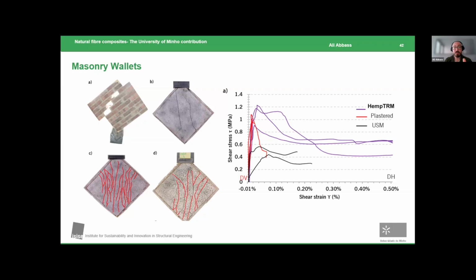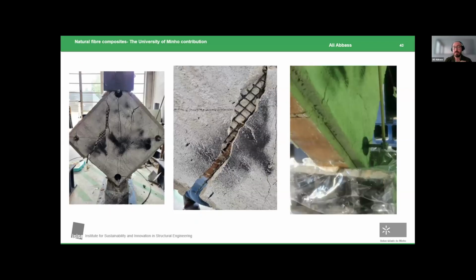The plastered ones, although they achieved nice shear stresses, had zero ductility technically. In the non-reinforced wallets, you would see this kind of super pseudo-ductility, and it's not related to the structure itself. It's just for the strut effect, so it's not real. So the purpose of the fiber inclusion in the composite system was super achieved. Here you would see some fiber ruptured upon the testing, although we have observed some kind of delamination due to the surface finishing of the bricks, but this is something we could test in the future. We could get over it.